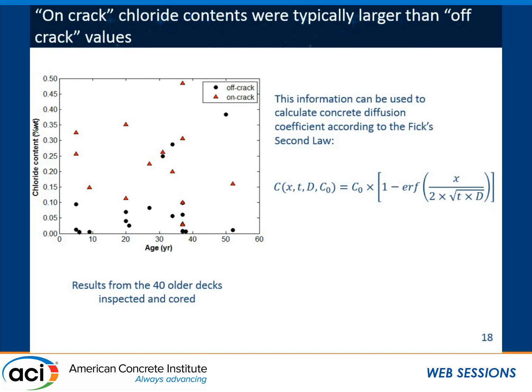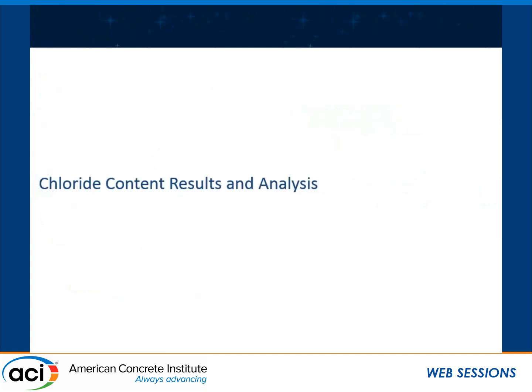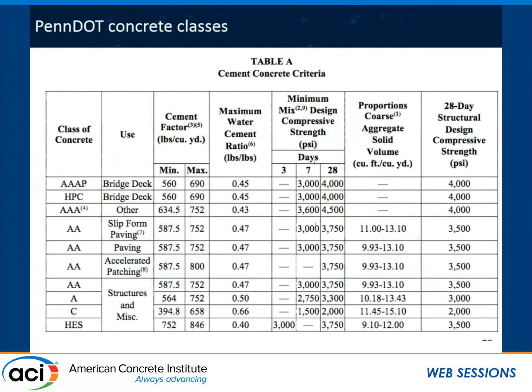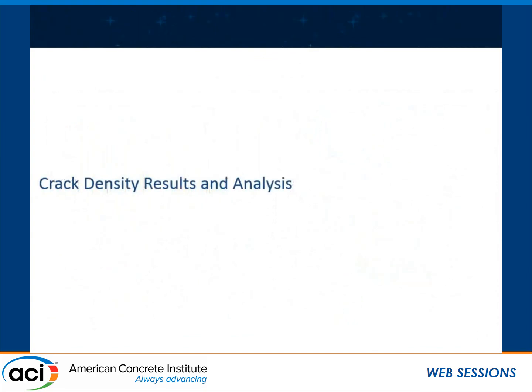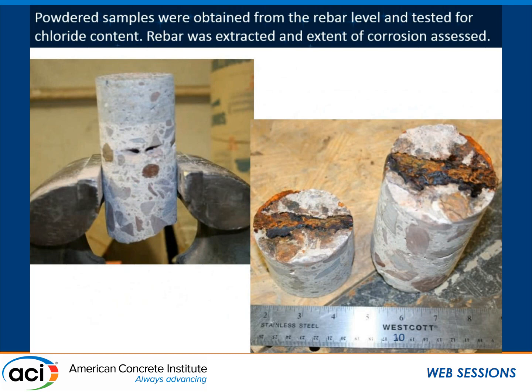Were you measuring just near the crack or across the full width of the core? It's a small area within the vicinity of the crack. I can't tell you if this is a cracked sample or not, but here you have a rebar, and here are the holes that were drilled to extract the concrete powder. If you had a crack that went down here, you would powder the sample, essentially at least half the thickness of the core, if not the full thickness. You extract the powder and measure the chloride. That's pretty much what we call the chloride content at the level of rebar in the location of a crack.